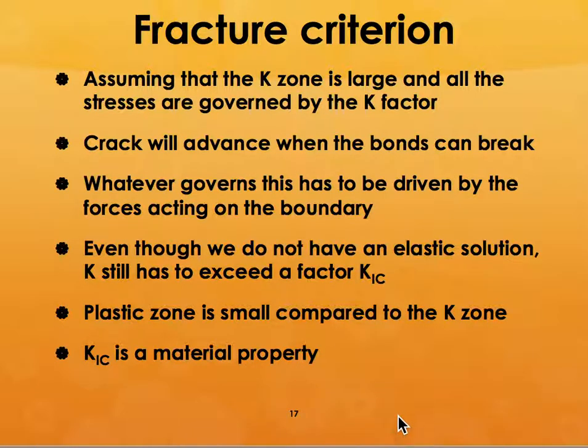In brittle materials, you have to understand that this plastic zone is small compared to the K zone, and I want to emphasize that K1C is a material property. So the material is going to control the critical stress intensity factor, and how the material is going to behave in the presence of an applied stress is going to be determined by the critical stress intensity factor of that material.